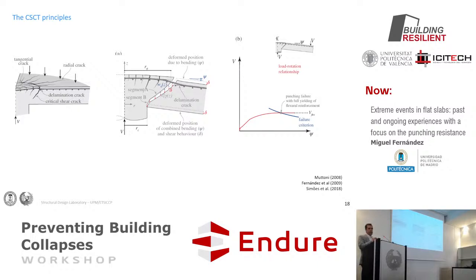And this is what we see, unless you have greater reinforcement and then it breaks during the plastic hinge. So this is the resistance that we have at this point. And then we can see it as the crossing between two curves. One is the failure criterion, which defines the capacity that we have for that level of opening of the cracks. The other is the load-rotation curve, which is the demand. So how much shear are we introducing for that level of rotation? And when they cross, when they intersect, then we have failure.